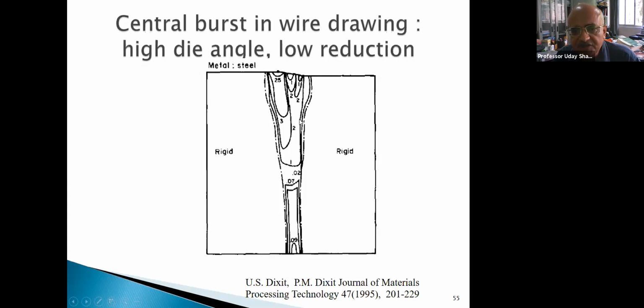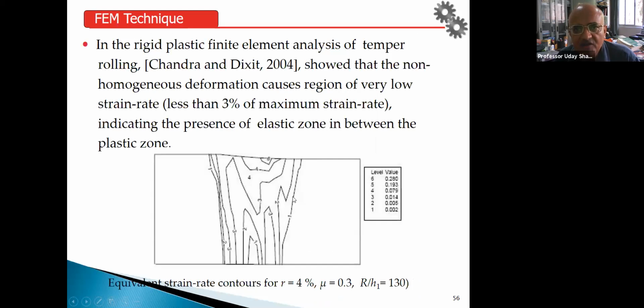So by observing such a flow pattern or deformation pattern, you can predict the defect and get some idea. Similarly, in the temper rolling process, we do a very small amount of reduction. The purpose is only to reduce the softness of the material, that means you just want to make it hard, and impart a good surface finish. In that process also we observe that there is some elastic zone in between, which may create problems.